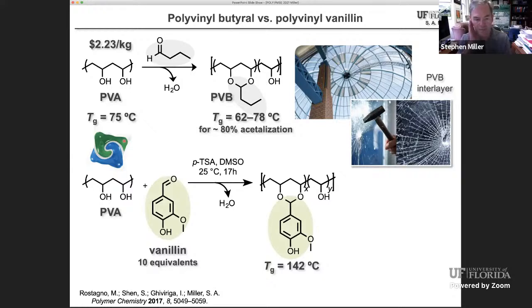And so what we started with this project was to attach bio-based aromatic aldehydes to polyvinyl alcohol instead of this flexible aliphatic aldehyde. And when you do that, you get a very large boost in the glass transition temperature. So here's vanillin, which is, of course, primarily a synthetic molecule, but still about 15% of the world's vanillin is made from the lignin of Norwegian spruce trees. So it is a bioavailable molecule, not particularly cheap. And you can attach that to polyvinyl alcohol.